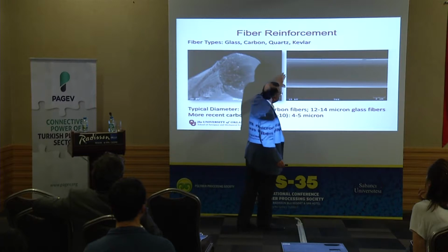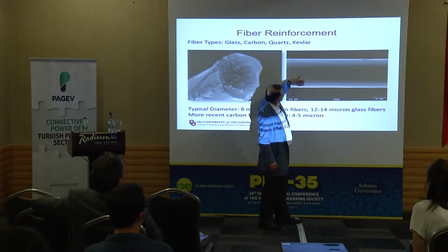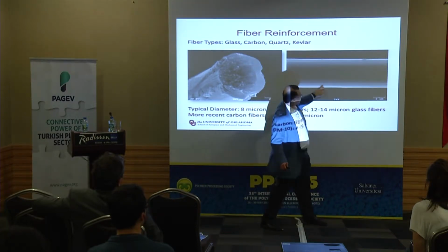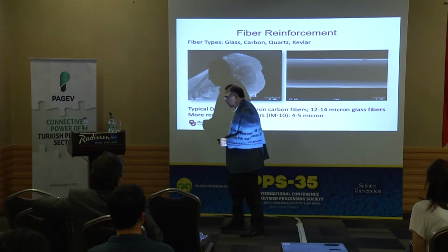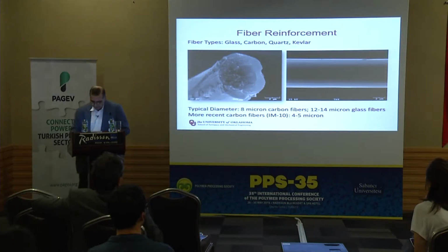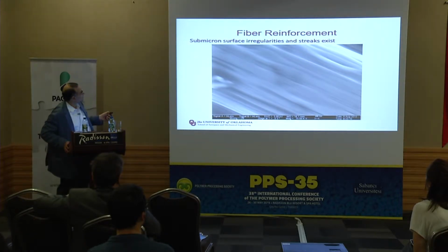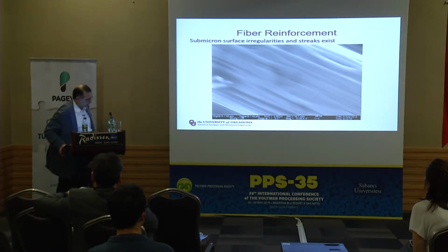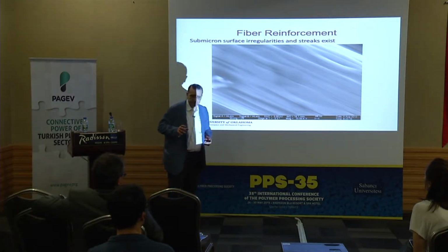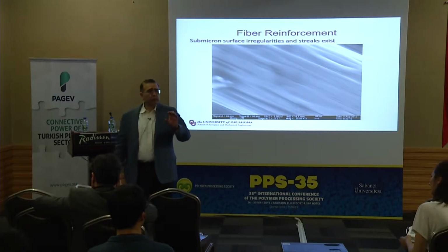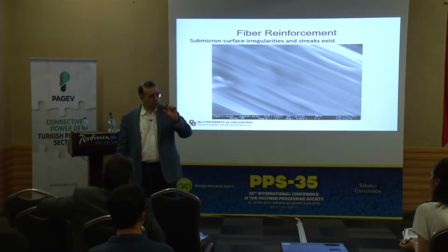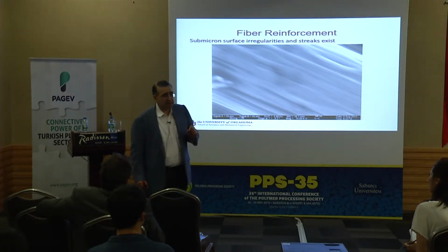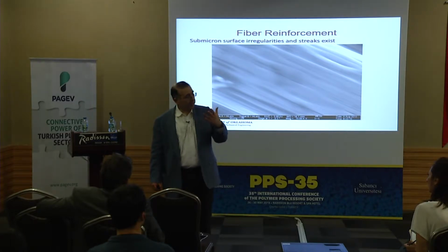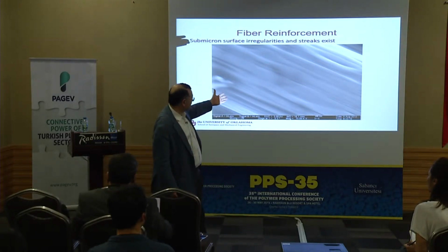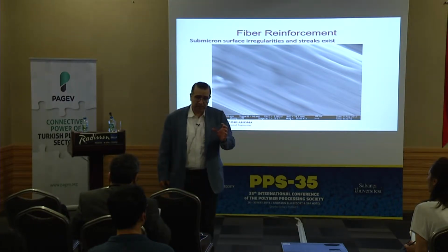If you look at this, this is 5,000 magnification. You will start seeing some surface texture. There are some streaks like these coming from the production. And if you really zoom in at higher magnification on these fibers, you will have some sub-micron surface texture. These kinds of streaks are visible on these fibers. Now, depending on the fiber, you will have a sizing on the surface, so-called sizing. And this sizing is usually less than 1 micron thick. You will not easily see it under SEM, but the surface has a very thin layer of coating.